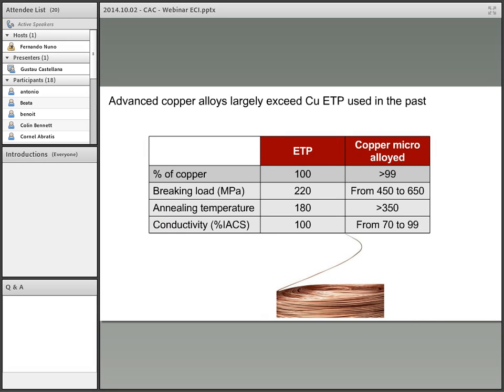Before starting the main presentation, I wanted to show you the main properties of this copper microalloy. Here in the table, you can see the ETP properties. You can see how the copper microalloy has been improved in a way that just adding 1% or less than 1% of alloy, we can double the breaking load, or even more than double, 3 times, and we can increase the annealing temperature a lot.